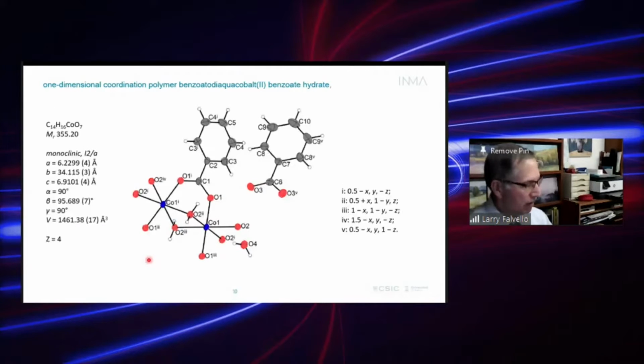Back to the structure. This is a structure that has a little bit of symmetry. The space group is I2/a, which is a different orientation of a space group that could also be set as C2/c, which is a more familiar setting, I think, in most cases. Cobalt atoms are on a center of symmetry. There's a twofold axis that goes through, let's say, the first two atoms and the para carbon of the benzoate, right?